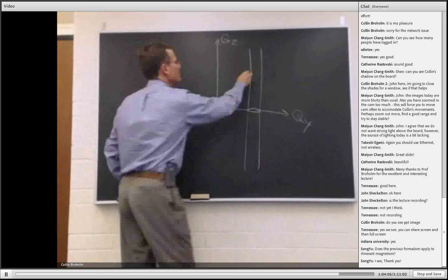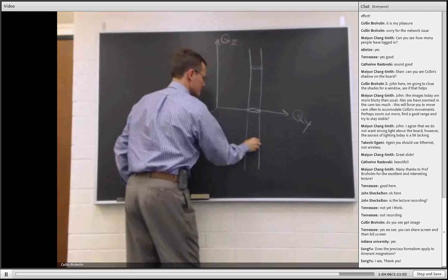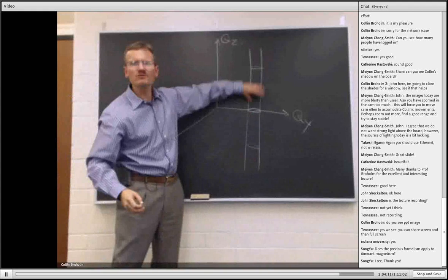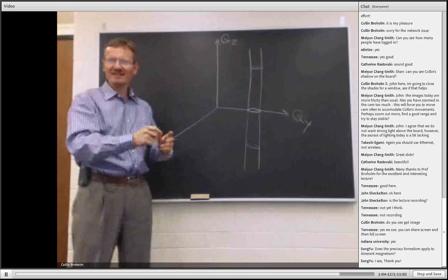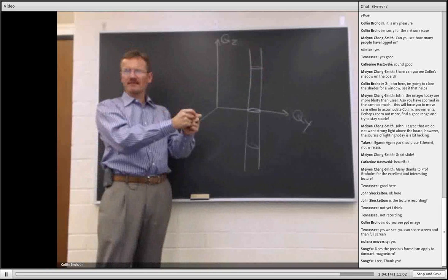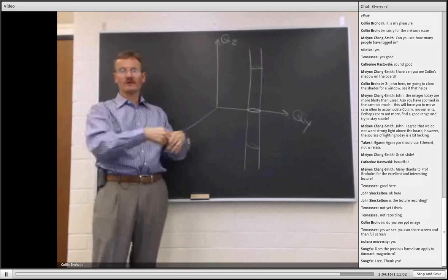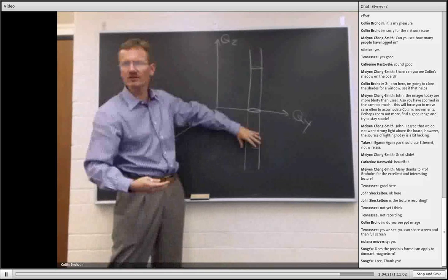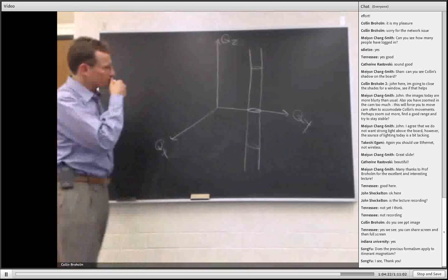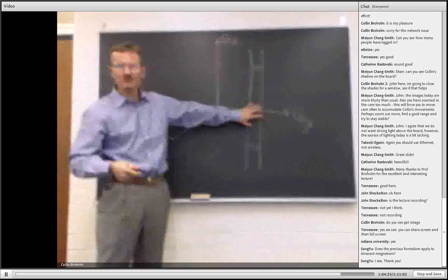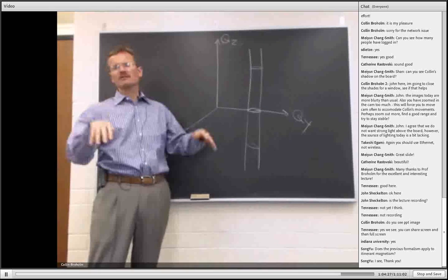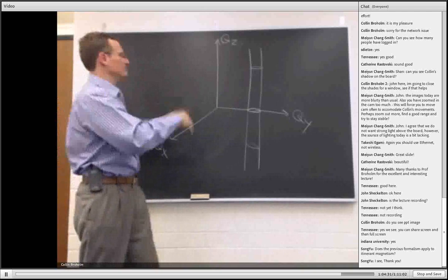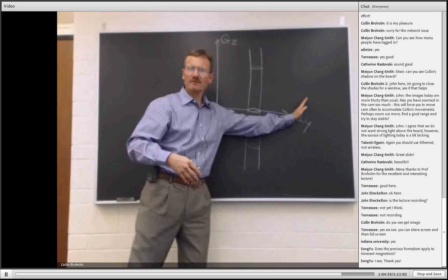So my diffraction cross-section, if I actually had a single crystal, would be in the form of a tube of scattering. Instead of a sharp feature in momentum space, like a Dirac delta function, as we would have in a three-dimensional crystal, I have this very oblong tube. I've only drawn one of those tubes, but if I had a hexagonal crystal, I would have 6 of those tubes typically, and then I might have some higher order tubes up here as well.